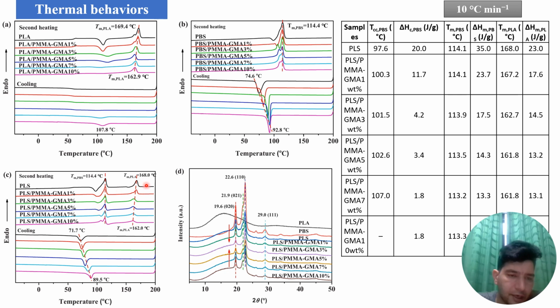Looking here, because of PLA it is 168 and it decreases to 162 because of the miscibility. Because of the miscibility and also nucleation of crystallization, the Tm of the PLA portion also decreases. And the Tc, the cooling crystallization temperature, also increases, which shows that the compatibilizer helps in the nucleation effect, in which crystal formation is dominant. So looking at the XRD,